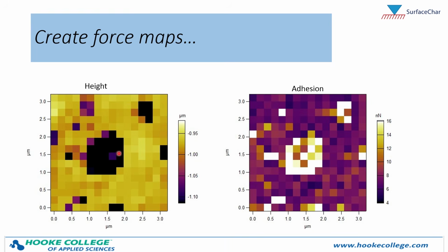From those individual force curves, we can measure that adhesive dip and get an adhesion measurement in nanonewtons here, adhesion force, if you will. Not surprisingly, showing that the rubber has significantly higher adhesion than the surrounding thermoplastic. So our rubber domains here, here, here, on the side, clearly showing significantly more adhesion than the thermoplastic. Not a surprise.